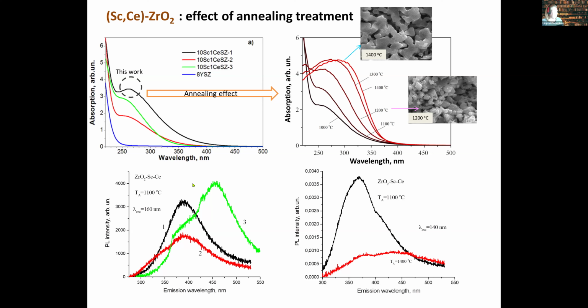At first, we measured here at DESY photoluminescence under 160 nanometer excitation. We observed that for 3 powders that have nearly the same chemical composition, we have completely different spectra. Powders 1 and 2 are more or less similar, but the third powder was completely different. A specific emission band appeared in this powder. Checking annealing treatment for the same powder, we discovered that for one type of powders there is a decrease in intensity, while for another type the intensity increases.